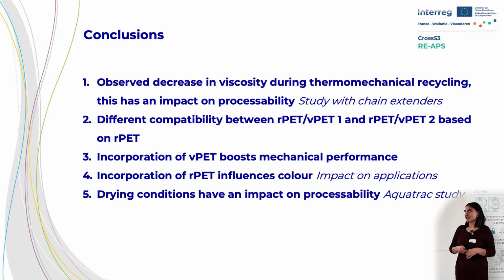different studies such as... just to summarize, the conclusions from these 3 case studies are that we have observed a recycle. This has an impact on our next step from the materials that we have in-house. We have seen there are different compatibilities between the recycled polyester and different virgin polyesters. Therefore, it's always interesting to look for some affinity of one of them to the virgin. We can see that the incorporation of virgin polyester in bicomponent configurations helps us boost the mechanical properties of the fiber. We can see that there is a clear influence of the recycled content on the color of our fibers, so that is going to have an impact on the dyeability of our textiles.